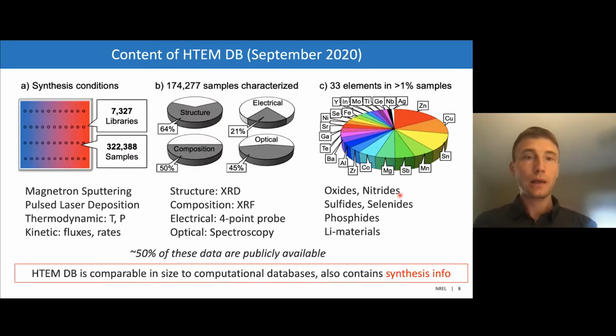So here's the content of HTEM-DB, the high-throughput experimental database for short, as it was approximately a year ago. At the time, we had more than 7,000 sample libraries, these objects that we create with composition or temperature gradient in our high-throughput experimental materials chambers, each of which has approximately 44 unique points on which these libraries are mapped, resulting in more than 300,000 unique samples or entries in the database.